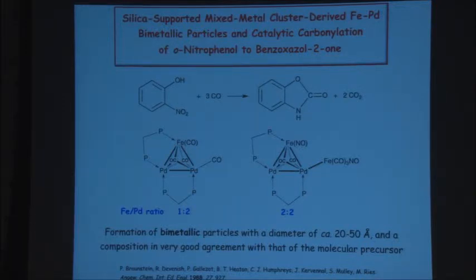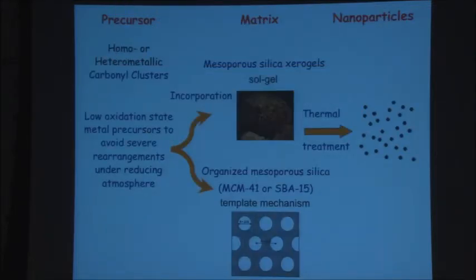That remains always a question mark you have to keep in the back of your head. So we thought about another way, or maybe a more refined way, to anchor clusters into porous materials. Typically, you have the precursor, which are the carbonyl clusters I mentioned, homo-heterometallic. We want to have oxidation state as low as possible in the precursor, so that when you strip off the ligands, you don't really have to do a drastic change of the redox properties of the core, to minimize the transformation. Basically, the molecular striptease we're doing to the terminal ligands should be very soft. Just remove the ligands without massive redox chemistry.